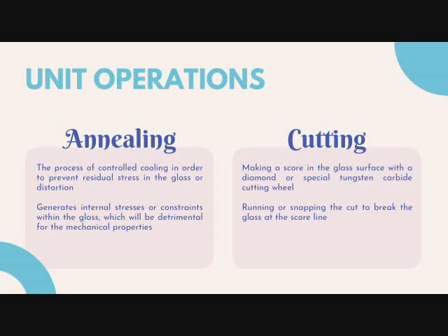Non-annealed or poorly annealed glasses will be subject to low resistance to cracks or failures under small thermal or mechanical shocks. All along the cooling process, the viscosity of the glass increases from a low viscosity melt to a rigid material with a higher viscosity. A certain degree of freedom is necessary for the glass to relax the constraints caused by the rapid cooling, causing rearrangements in the glass structure. Good annealing can only be obtained in a relatively narrow range of temperatures. For a good annealing of the constraints, the viscosity of the glass should not be too high so that constraints may no longer be released, and not too low so that the glass will not retain its initial shape.